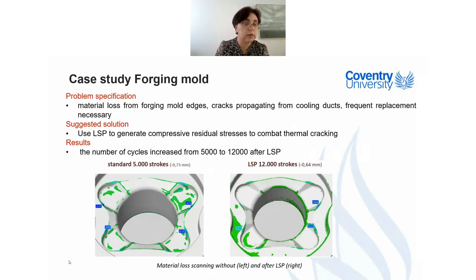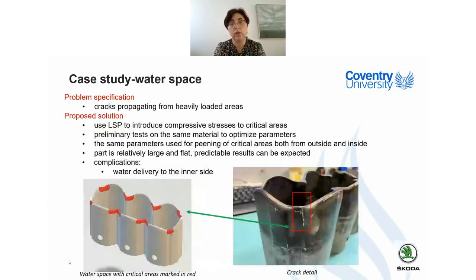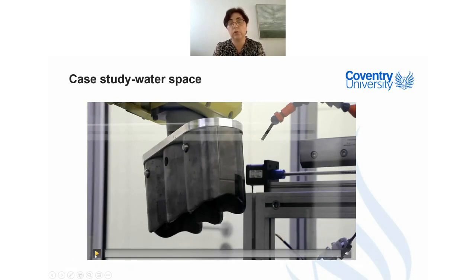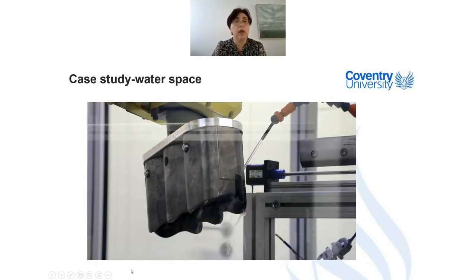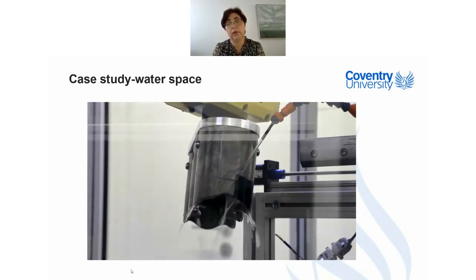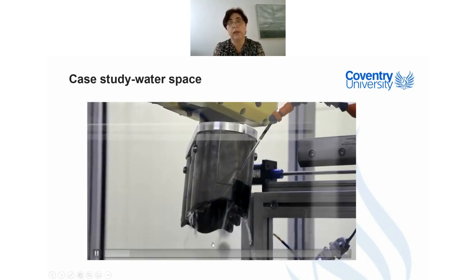Now I have to switch the laser pointer again in order to show you the video of how this part was treated. We are treating only this red part which was shown in the image in the right corner. The green light is not a laser, it's just a diode light showing where the treatment is done. As you can see, we are using a 10 Hz laser, but the speed of the process here is mostly defined by the speed of moving the parts. So I think to increase productivity it would be better to use a very similar arrangement to what Curtiss-Wright is using.